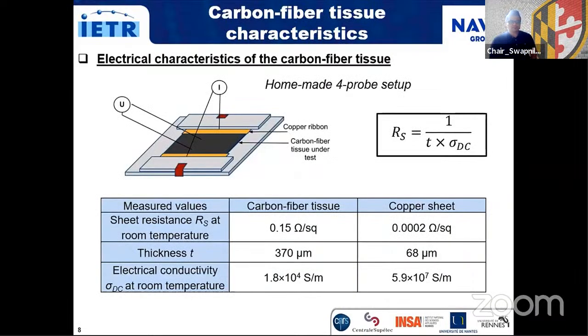Now, let's move to the electrical and dielectric characterizations. First, the electrical characterization of the carbon fiber tissue with the 4-probe setup. As expected, the sheet resistance of the carbon fiber tissue is larger than that of the copper sheet, but its value remains satisfactory in view of microwave applications.